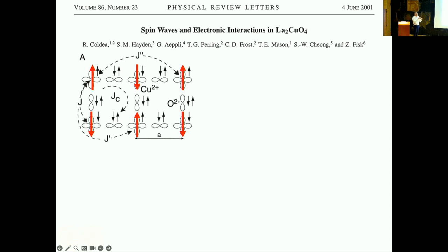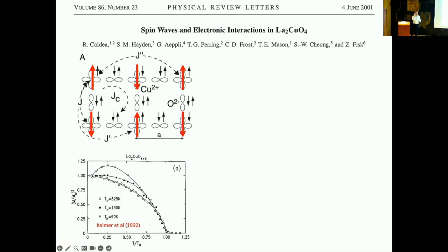So sites which were previously indistinguishable in the paramagnetic phase now develop a net magnetization which is staggered from site to site through the lattice. The way you notice that in neutron scattering is by the appearance of a new Bragg peak, because the translational periodicity has now changed. This used to be a reciprocal lattice vector in the system, but now that takes you from an up spin to a down spin. So that implies that there's a new Bragg peak that develops. And by monitoring the temperature dependence of this Bragg peak, you actually probe the staggered magnetization of the system.